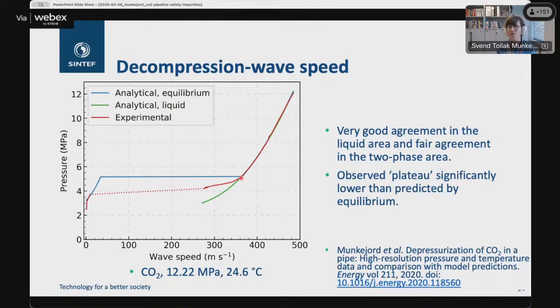So if we assume full thermodynamic equilibrium, then our model tells us that as soon as we have any vapor present, the wave speed jumps down to the value here. Now, instead, if we assume that the liquid would stay liquid, metastable, then we get the green curve, and our data shows something in the middle. So this does not mean that the Span-Wagner equation of state doesn't work. It only shows that in this case, the process is so fast that there is no equilibrium.